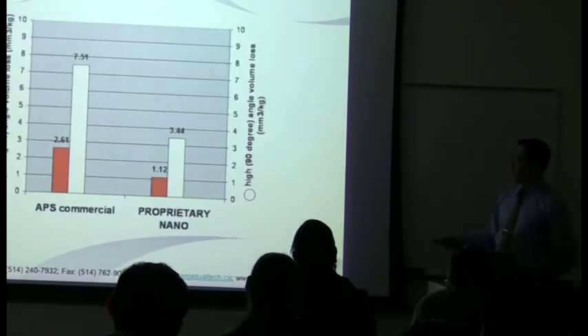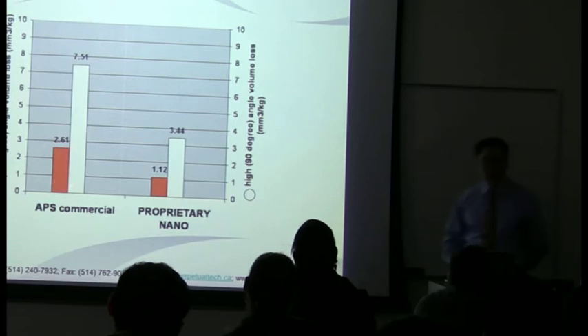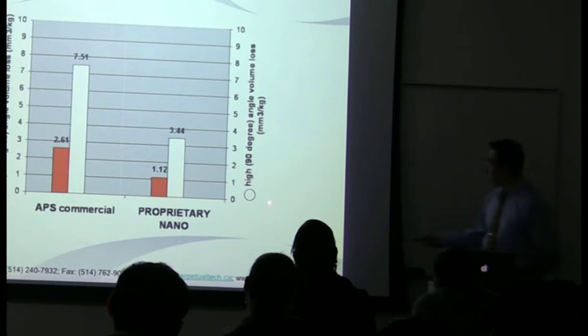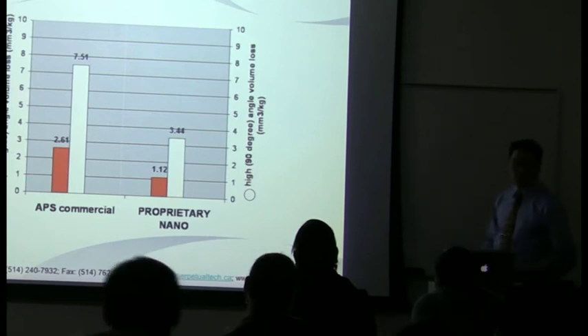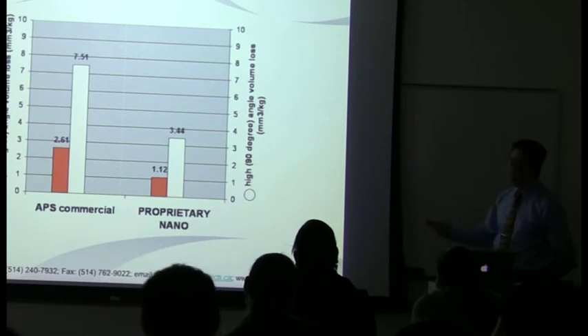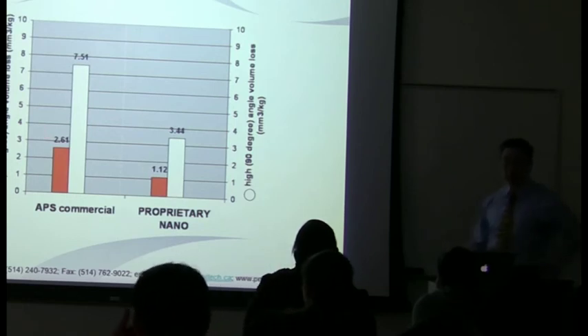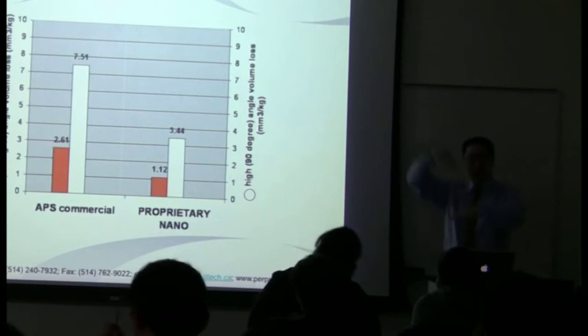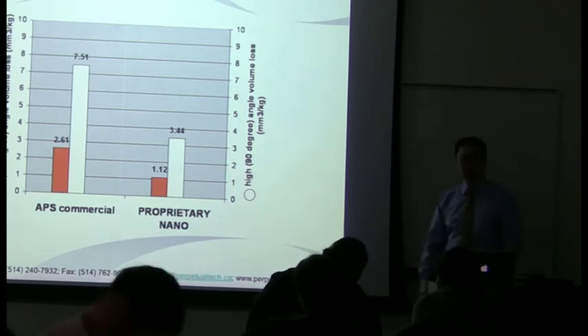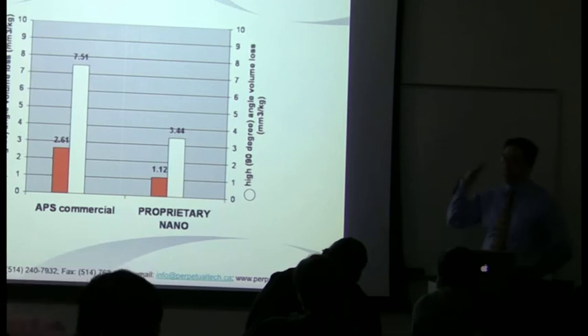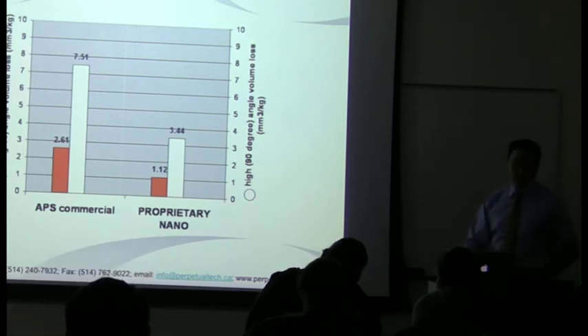And here are the results. In the orange columns, these are wear or volume loss at low impingement angles at 30 degrees, and then here's the 90-degree high impingement angle volume loss. And this, once again, is unique. No one has seen that before, where you have a decrease in both low and high impingement angles. Typically, if it decreases for a material, it will increase at the opposite impingement angle. However, because, once again, you've got something harder and stronger and something even tougher, you can have direct improvement in both impingement angles. And that's really good.